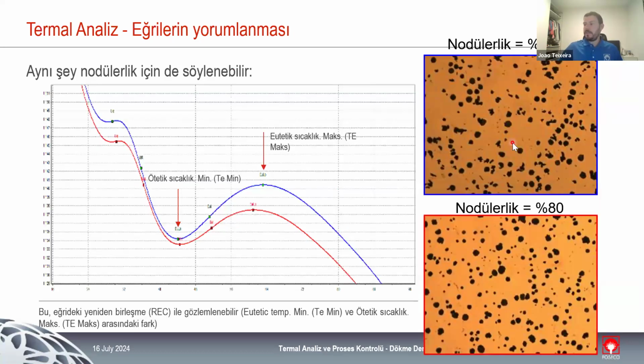And another important aspect of nodular production is the nodularity and the control of the recalescence, the difference between the eutectical minimum and maximum. And you can see that when this recalescence is lower, we have a high nodularity, around 80%. And when it's higher, we have a lower nodularity, around 65%. So recalescence is also an important parameter to control in thermal analysis during nodular cast iron production.